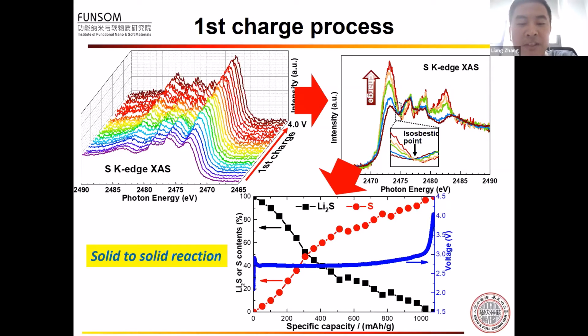By using a linear combination method, we can directly derive the content of lithium sulfide and sulfur as a function of state of charge. The black curve is the lithium sulfide, and the red curve is the sulfur. We can clearly see that the content of lithium sulfide is gradually decreasing and the sulfur is increasing. These results clearly indicate the first charge process is a solid-to-solid reaction without the formation of lithium polysulfide. Because lithium sulfide is like an ionic crystal, it's very difficult to extract the lithium from lithium sulfide. Therefore, for the first charge process, a high cutoff voltage is always necessary.